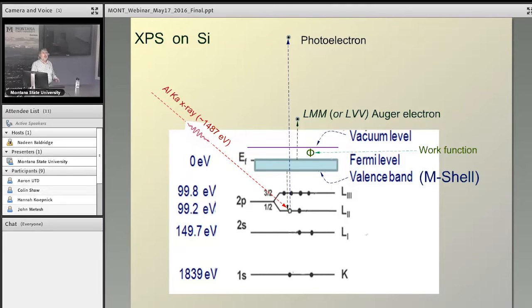But as I said earlier, the system is very efficient. Unlike our government, it immediately stabilizes itself, immediately takes care of its problem. It fills this hole within 10 to the minus 13 seconds, and in doing that, it can generate an X-ray. But half of the time, we don't teach this in physics, and I don't understand why we don't. Half of the phenomena is the Auger process, the other half is X-ray emission. So you shoot out another electron.